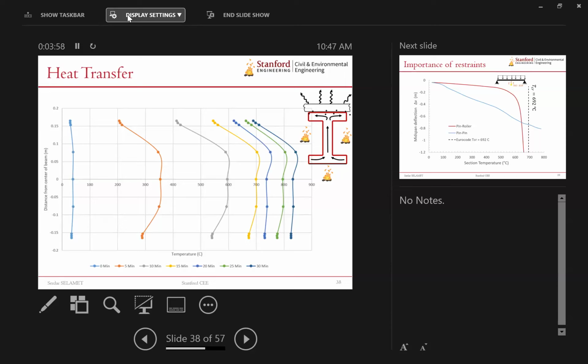5 minutes, we have a temperature distribution throughout the fibers like this, okay? Lower temperatures on the top flange and higher temperature on the bottom flange, and actually high temperature in the web as well because the web is very thin. And then we get up to 10 minutes, 15, 20, 25, and 30. So this is sort of the last phase of the heating, okay?